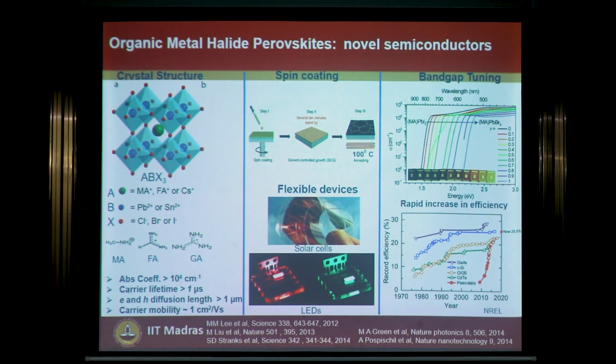The important physics behind is that it has very long diffusion lengths and very high mobilities. Why do they have long lifetime? Is it because you could make them defect free, or is it because? Oh, nice. What other things? So I'll come to the defects at a much later stage. What causes the long lifetime? So it's not defect free. We have a lot of defects, but it is defect tolerant.